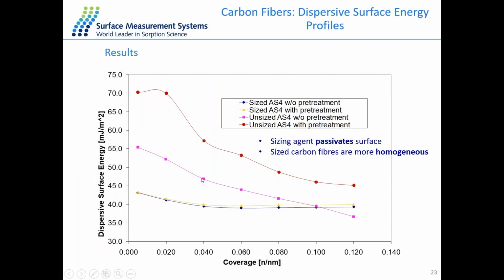So here we have a different kind of graph to what you saw previously. Here we're looking at the dispersive surface energy against our coverage. We have injected different concentrations of our probes onto our material to obtain certain coverages across our surface. Here we have our smaller concentrations in infinite dilution, and here we have our higher concentrations. If we just look at these two here, this is our sized material. As you can see, they are more linear as compared to the unsized material, which has a more ranging profile.